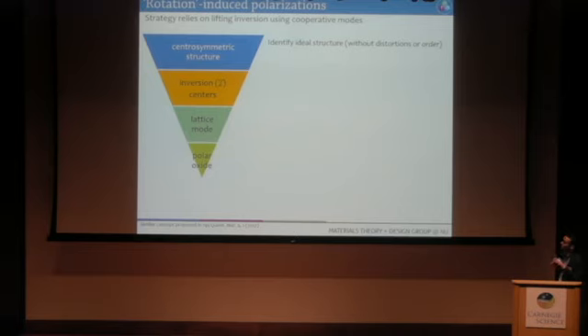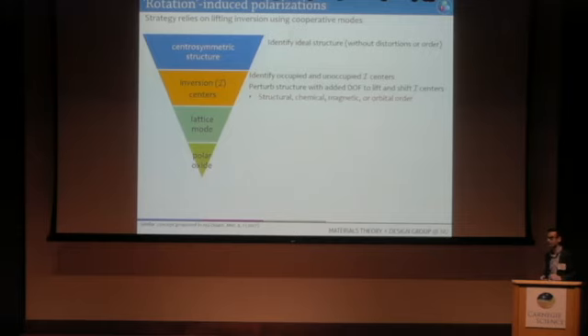And the manner in which you design these materials is you start with a centrosymmetric structure without necessary distortions, an idealized case. You identify occupied and unoccupied Wyckoff positions in that space group, so this is just a crystallography problem. And then what you do is add some degree of freedom. So you're going to perturb that ideal structure with some other feature. It can be structural, like a rotation. It could be chemical order. It could be magnetic order, and we heard about that yesterday.